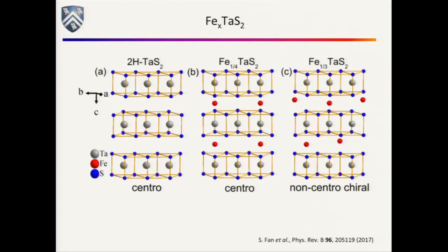So basically one of the d electrons on the iron is the operative one here. These things actually end up being in a high spin state because of the crystal fields. And there's still a bunch of debate, and on some level this is really where the correlations come in. There's a significant orbital moment contribution to these things, as well as the local spin degree of freedom. Spin orbit coupling is important. So these are challenging materials to understand.